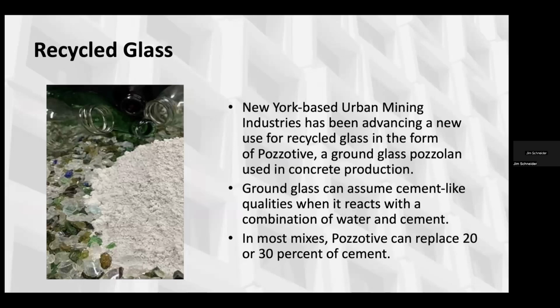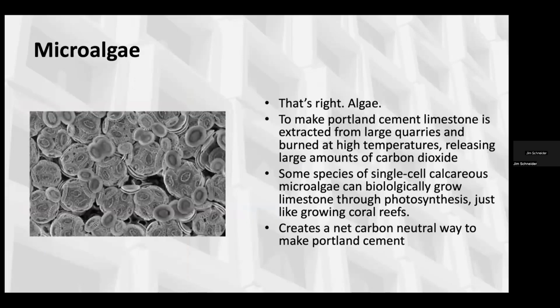So basically, it starts with a chemical reaction when it's paired with water and cement, and the hydration of cement introduces two key compounds. One is calcium silicate hydrate, which is basically the glue that develops the concrete strength, and the other product is calcium hydroxide, which conversely weakens the concrete and causes porosity. When a ground glass pozzolan is introduced, it gives up a silica atom and joins in the CH to become CSH. So the pozzolanic reaction allows ground glass to gain cementing properties and act as a partial replacement in most mixes, usually about 20 to 30%. So there's some interesting possibilities there too. That's a little bit more localized. I don't know if that's really gone much nationwide yet, but we have seen some work with that.